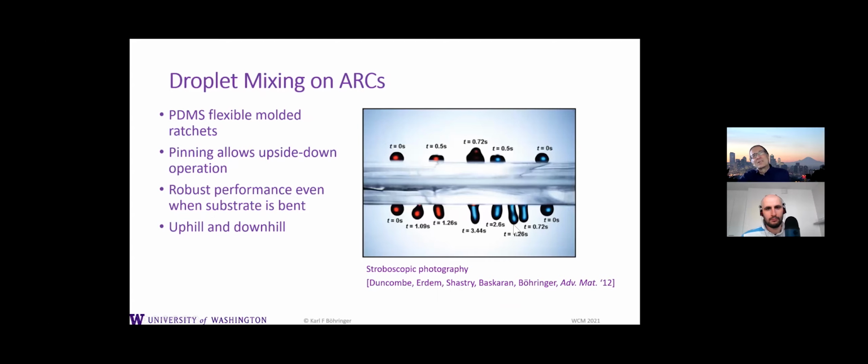Now, what's maybe even more surprising is that you can make this droplet transportation system work in some very unexpected ways. For example, here you see drops that are moving in this stroboscopic image on the top of a surface. This is made with PDMS, but also hanging drops that are clinging to the surface roughness, even though we think of the material as super hydrophobic, but at the same time, the roughness creates pinning forces. That's where the drops essentially are holding on and moving from left to right here for the red drop, from right to left for the blue drop.